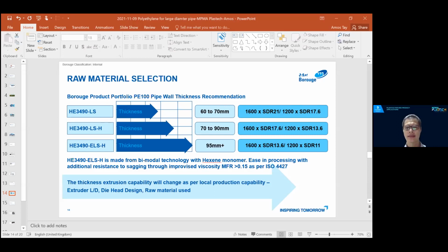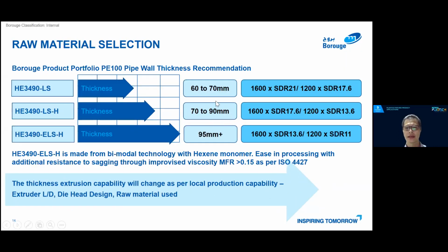It shows here that for the required thickness, if you are running around this thickness, LSH could be used. It has intrinsic low sag performance, not because we designed it this way, but because first grade LS is a butene base, and LSH is a hexene base, and we designed this hexene base for high stress crack resistance. That means when you cut a groove on the pipe, the slow crack growth takes a longer time to crack through the wall.